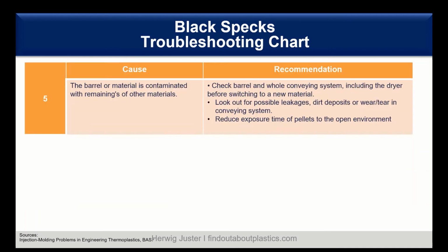Okay, and then another cause is that the barrel or the material is contaminated with remainings of other materials. It's also what we already discussed in the reasons of black specks section. And here recommendations are to check the barrel and the whole conveying system, including the dryer, before you start switching to new materials. Also in the dryer there can be some remainings, especially when you use black pellets most of the time. So here it can often happen that same material or different materials get mixed with each other.